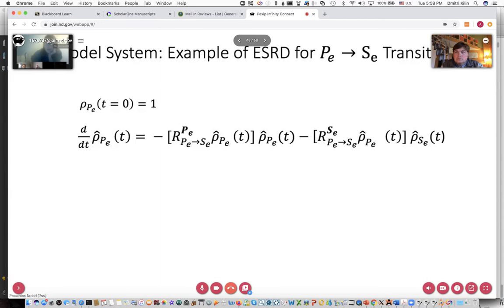And so I haven't filled this in yet, but this is just an example of how the dynamics would evolve. So say your initial condition is you have a charge occupying the PE band at time equals 0. And so the change in occupations of that band at time 0 will be weighted fully from couplings computed in that configuration. But as time goes on, you'll have population change from the P state to the S state. And so you have a gain in population in the SE. And so as time goes on, you'd have a weighted contribution of rates from both electronic states.